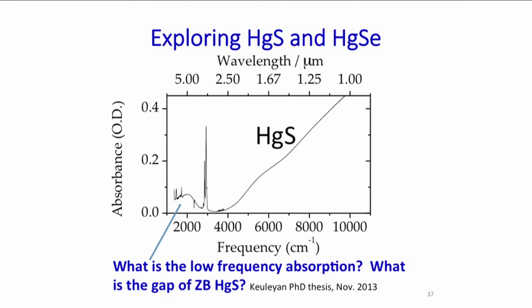So then we thought of exploring other systems. And since we looked at mercury telluride, mercury selenide, mercury sulfide are just the same in principle. So let's just look at them. And what we found to our surprise was mercury sulfide, well, the spectrum is not very pretty. It's kind of a broad spectrum. This is a peak which is due to the ligand in the films. So it's just a molecular vibration. But we also saw this band here, which was a puzzle. Where did it come from?